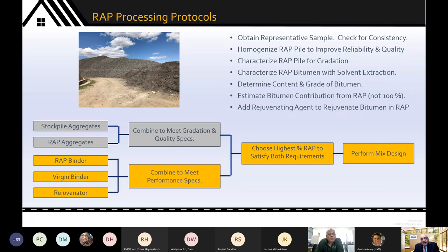So let's move on and ask, how do you actually do this in a lab? Again, very simple. You take your stockpile aggregate, you take your RAP aggregates that you've created those different piles of, you dry mix them in order to make sure that you understand the gradation, and you settle your RAP content based on how you're able to meet the gradation spec that your specifying authority has laid down for you. Remember, I told you previously, typically, if you have more RAP piles, coarse, medium, fine, you'll be able to incorporate more and more RAP in order to meet your gradation spec.